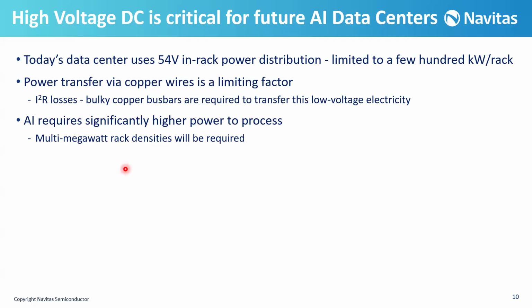Now, AI requires significantly higher power to process. And it means that we need higher power. So if we have a constant voltage, we need higher current. And again, we have higher power loss. So in other words, we need to increase the voltage instead of increasing the current. And this is the reason that the new architecture is required, plus minus 400 volts to 800 volt DC.